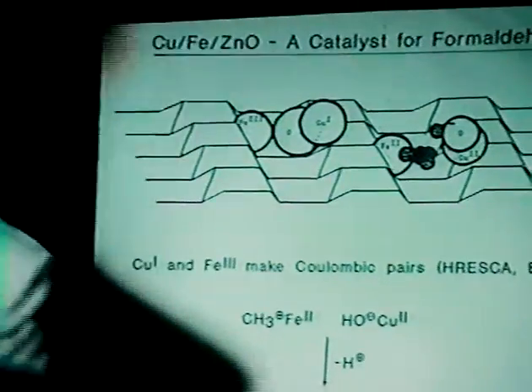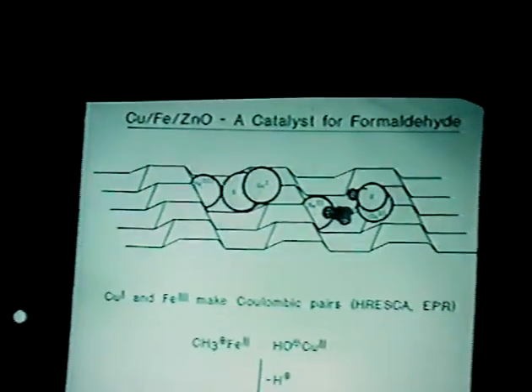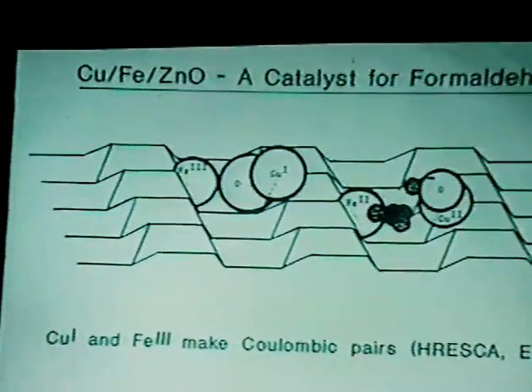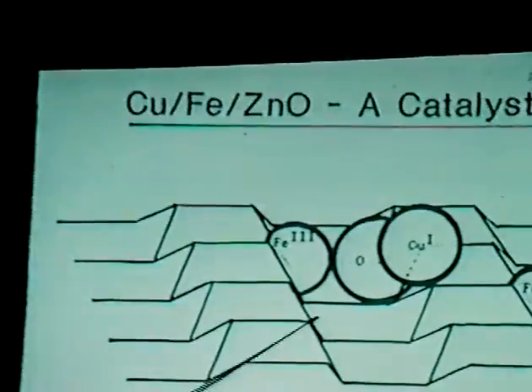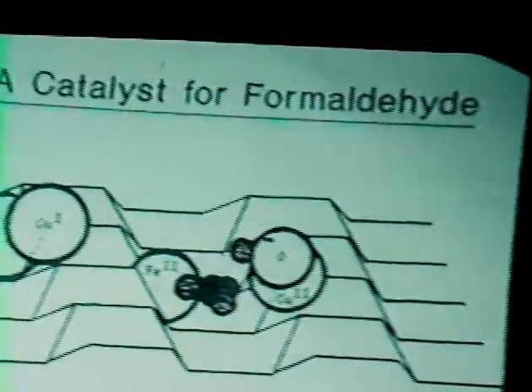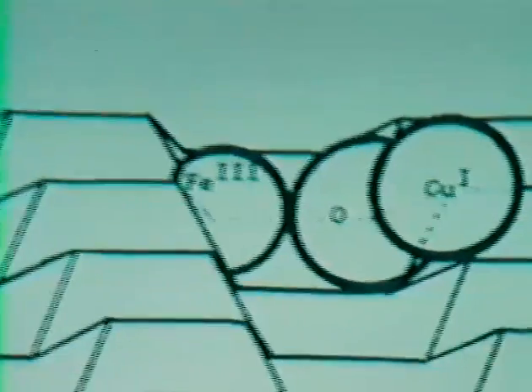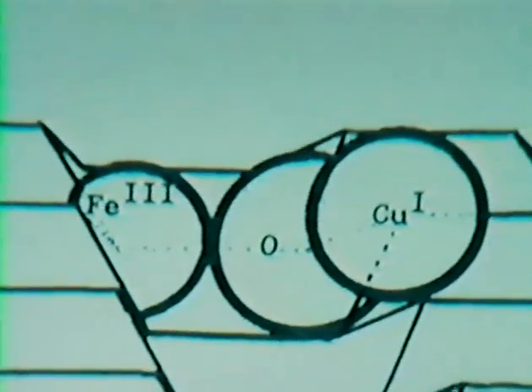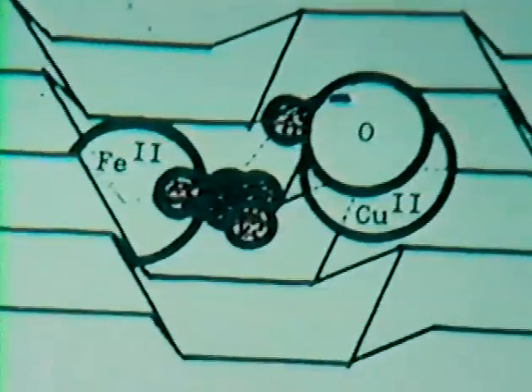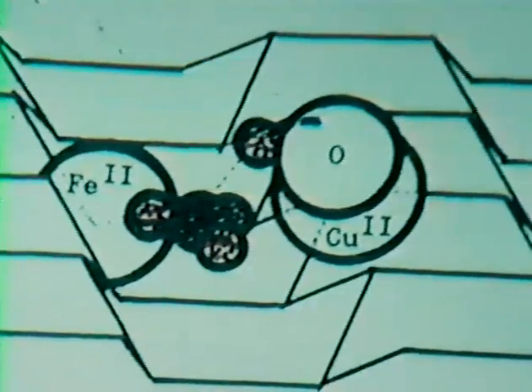So what we did, instead of using zeolites, which did to some extent work and did produce formaldehyde, we used our own old acquaintance, zinc oxide, which has zinc, oxygen. This is a stable plane of zinc oxide. And we, people who do oxidative coupling, know that zinc oxide is a moderate to poor oxidative C2 coupling catalyst.